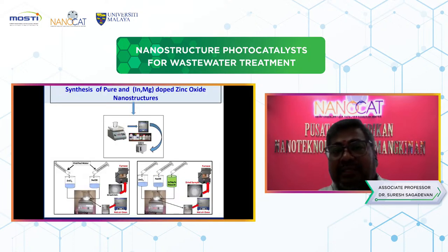Then we worked on two dopants, indium and magnesium doped zinc oxide nanostructures. These were prepared by a simple chemical precipitation method, which is very low cost. The zinc oxide is prepared using two precursors, zinc chloride and sodium hydroxide, mixed together. After the solution is prepared, it is kept in the furnace for 3 to 4 hours. After drying, it is washed with ethanol and water and dried. Finally, we prepared zinc oxide, and this is pure zinc oxide. As well as that, we prepared zinc chloride with sodium hydroxide mixed together, and we added the indium and magnesium dopants to the zinc oxide.